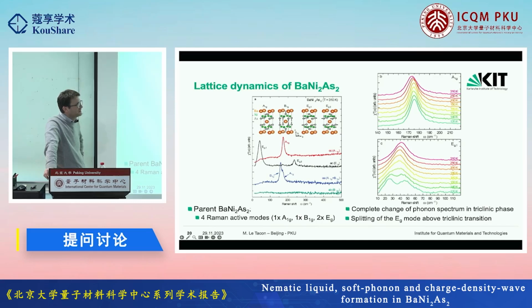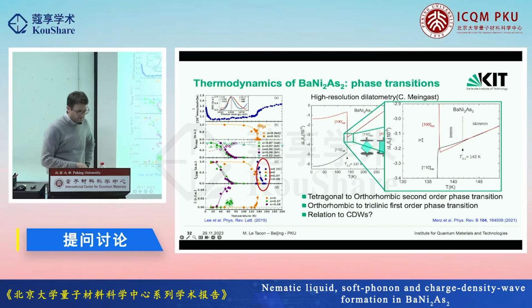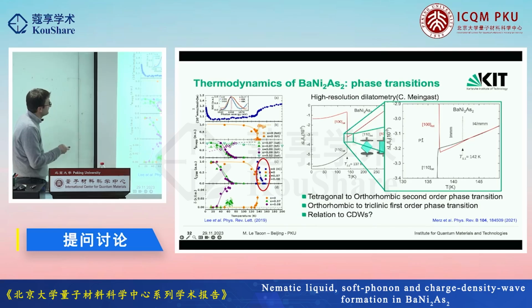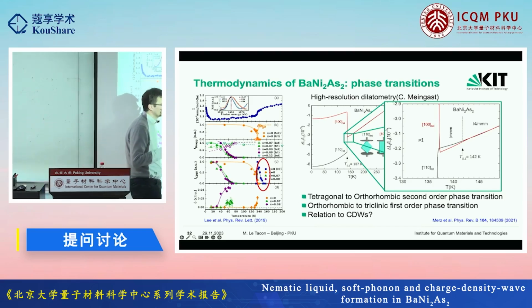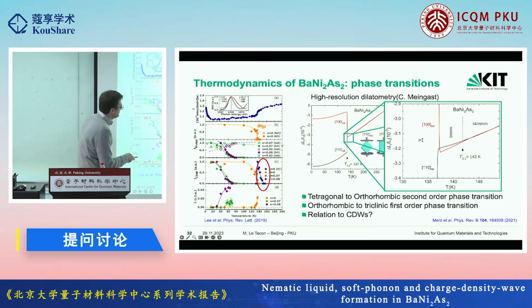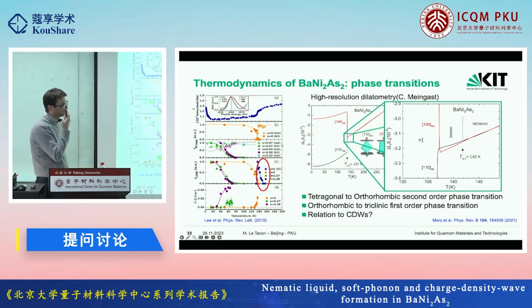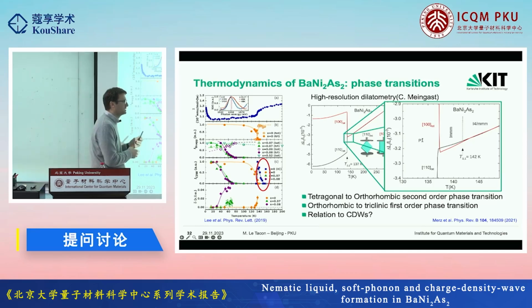And how about the magnetic field? Yeah. So actually, in the measurements by Peter, they characterized the transition here using the magnetic susceptibility. Yes. And this was measured with 1 Tesla. Okay. So you see this order here. This is 1 Tesla, and it's a very weak signal. So actually, magnetic susceptibility is not that great to study the system. It really doesn't show any magnetic order, which, by the way, has been confirmed recently by Marc-Henri Julien, who looked at these samples using NMR, and can definitely rule out any kind of magnetic order in that system. I see. So the nickel is just not magnetic in this case.